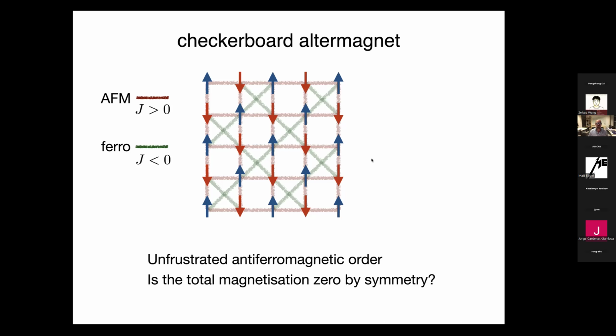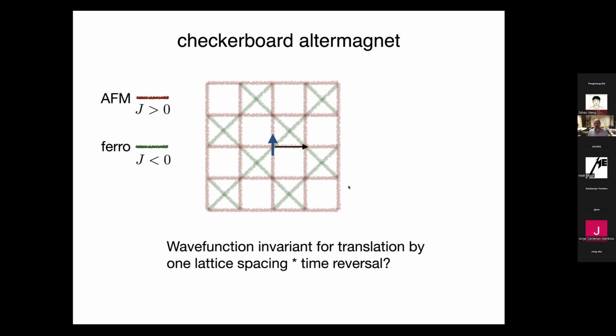But let's try to be a bit more precise and ask which symmetry enforces the zero magnetization of this antiferromagnetic ground state. And I would take the analogy with the antiferromagnet that I considered before and consider the translation of a spin from one sublattice to the other sublattice. So is the wave function invariant for the translation by one lattice spacing times time reversal? And that's actually not the case, because let's look at this spin here. It has these nearest neighbor antiferromagnetic bonds, but it also has these ferromagnetic bonds along this diagonal. And the fact that it has ferromagnetic bonds along this diagonal will be imprinted into the ground state wave function.